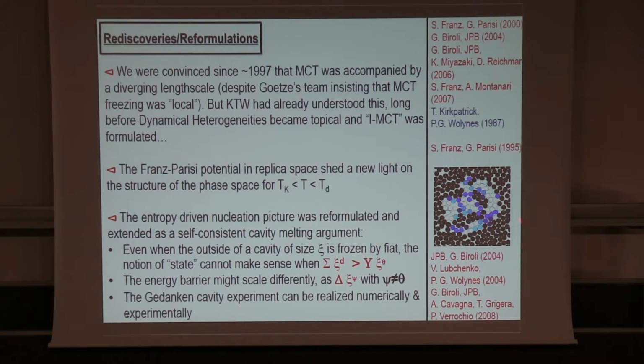So I guess that many of you have seen this picture, which I've stolen from a paper by Ludovic and collaborators. So the idea that we had is that even if you froze by fiat all the particles outside some cavity, then the notion of a state cannot make sense when the configurational entropy becomes larger than the pinning energy that's provided by these random boundary conditions. So in that case, one finds exactly the same scaling law as was anticipated in the 1989 paper, but I think on a slightly firmer ground.